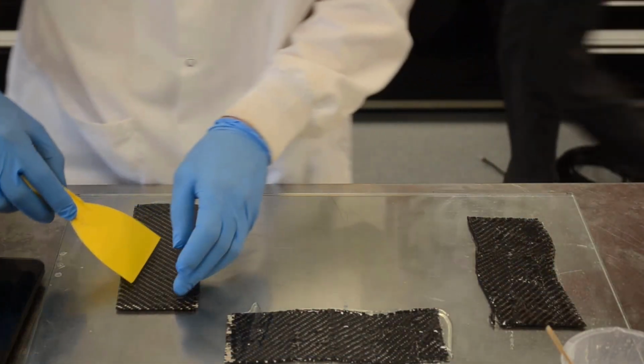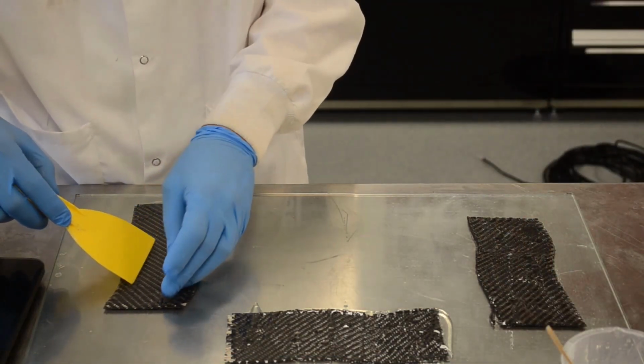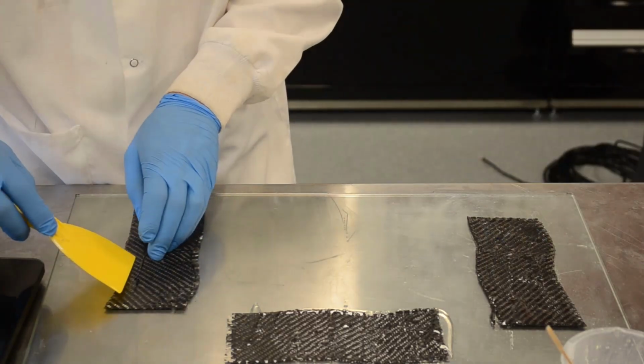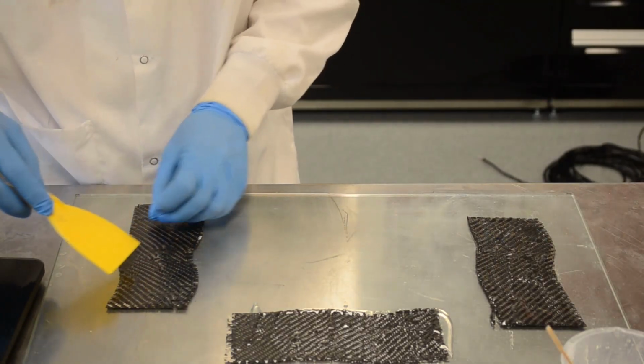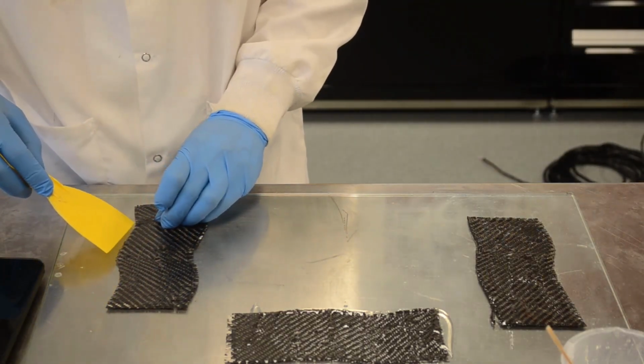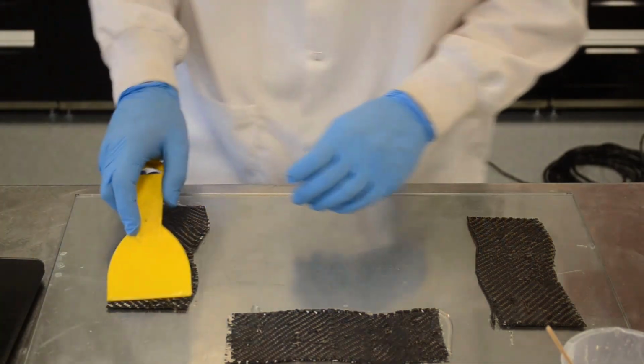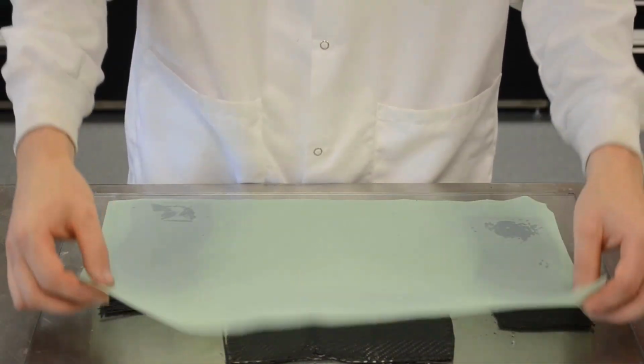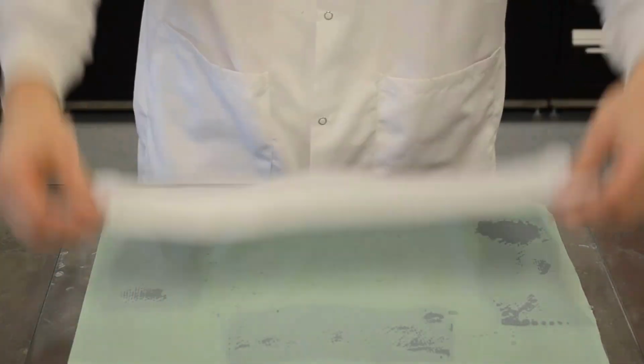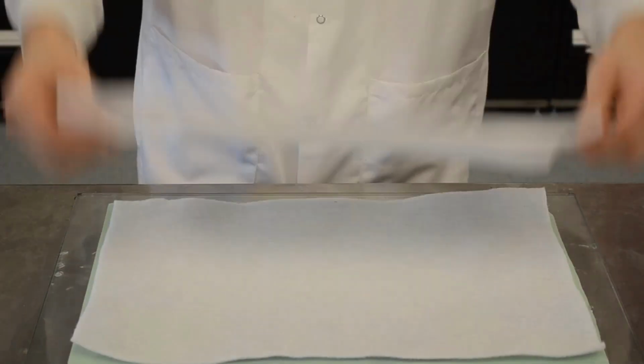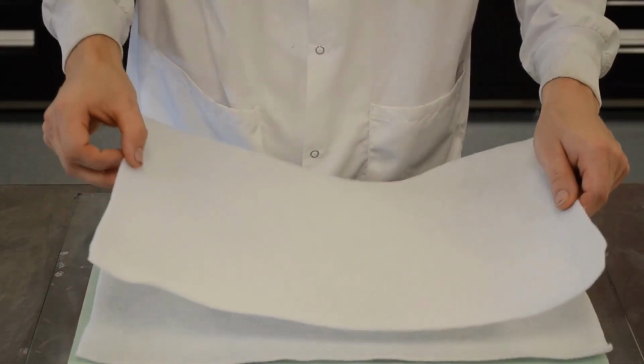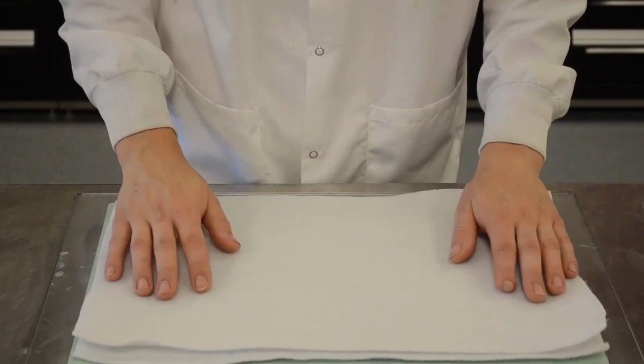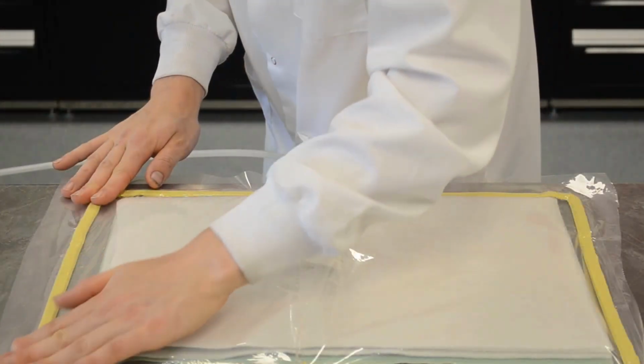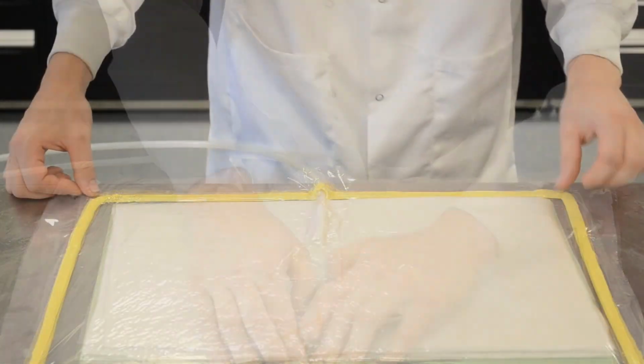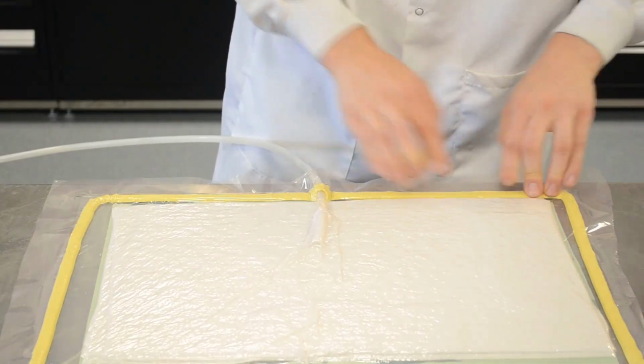For 3 of our samples, we will slightly deform our fabric while laying them up to observe the effect it has on part outcomes. After all plies have been deposited, we will place the vacuum consumables on some of the parts. We will place the peel ply against the laminate, followed by the breather cloth. A portion of the resin will be pulled into the consumables and increase the fiber volume fraction of the part. Breather cloth also helps to remove entrapped air, reducing large voids in the laminate. The samples will be left to cure at room temperature.